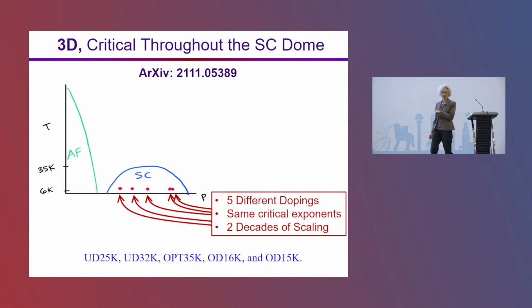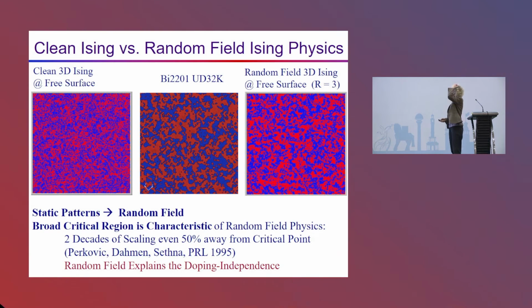That is curious because this is a very large critical region. This is not like the case of, say, superfluid helium where you have to get insanely close to the transition to see the criticality. This is a very robust, large critical region. That's a bit curious as well. And it's that broad criticality, the power law scaling out to the entire field of view through the entire doping range, that's actually helping us distinguish between the clean case and the random field case. That broad critical region is characteristic of random field models. You can get 2 decades of scaling even 50% away from the critical point in a random field model.